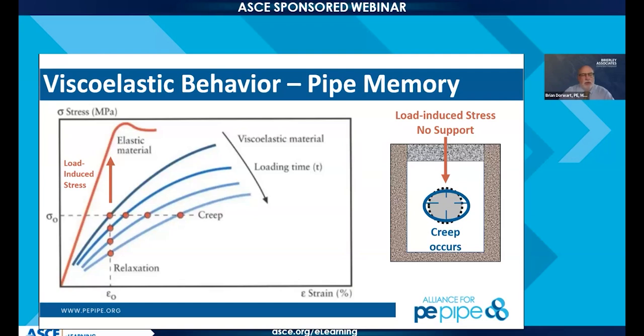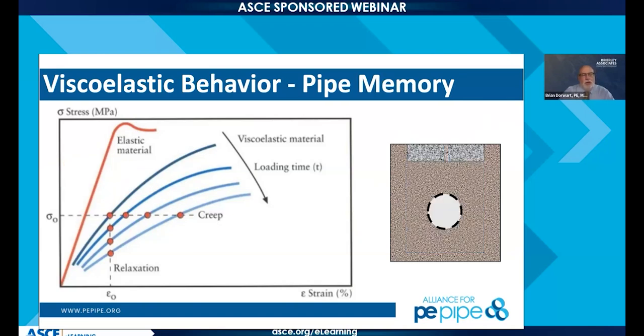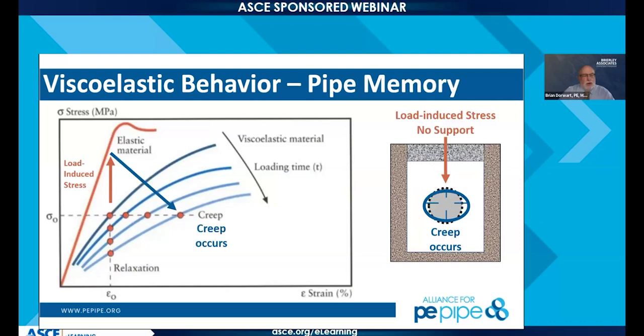Viscoelastic plastic materials, and it's not just HDPE, you can look at rock salt, rock salt's viscoelastic as well. It means it's going to creep. And the creep will cause that elastic curve, instead of being straight, to start bending over with time. So you're stretching on it. The modulus, which we use for design, you want to take into account the creep, and the modulus in the charts does take into account creep. It's part modulus of the material and part creep.